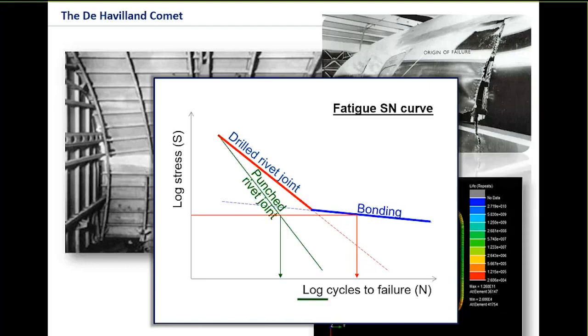Now, if we were to change that, as we did in the Comet, for a punched rivet joint, a punched rivet joint isn't as good as a drilled rivet. You see, with a drilled rivet, it's got a nice smooth edge, but a punched rivet has a rough edge, and those fatigue cracks can start a lot better with rough edges. So when we look at the real fatigue life on that log axis, it's significantly less than what the original design intended it to be. And this really is what caused the failure of the Comet so prematurely and early.